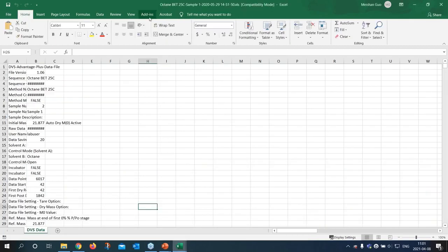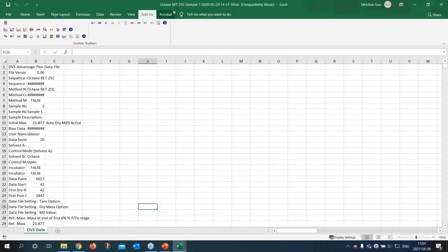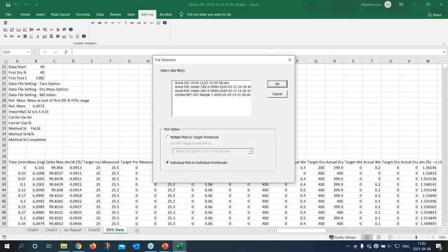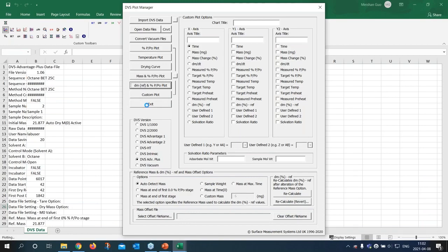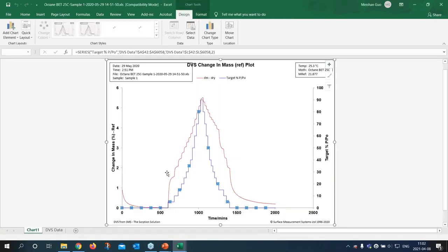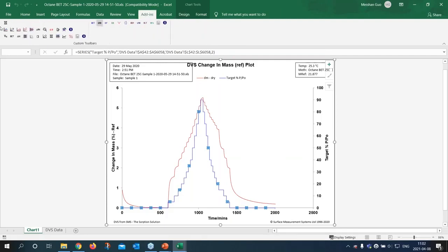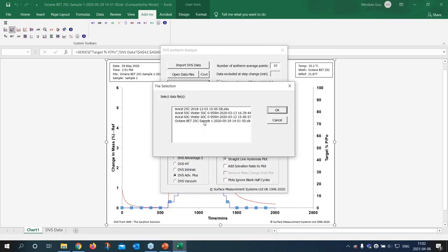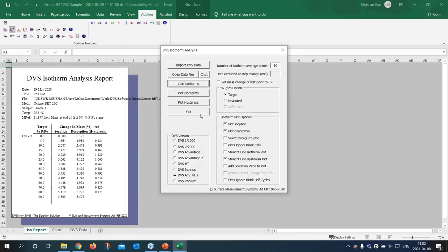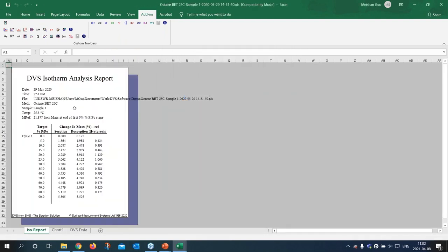But the last one I want to show is the BET calculation. So the same, we can perform the octane sorption at one sample for 25 degree. And here we get a very good octane sorption for this data with very good equilibrium. Then to calculate the BET surface area, we first need to plot the isotherm as well. With the isotherm data, we can then press the second button here, which is for the BET calculation.